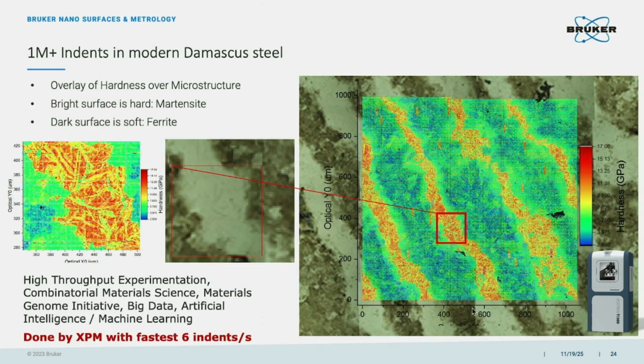So this is the example. We are using our indenter to do the high-speed mapping. We call it 1 million indents. Of course, this is extremely too much, 1 million, right? But just to give you the idea, because we are going very fast, right? Maybe 100 indents take just 30 seconds. So for 1 million indents, probably we need several hours, right? But even several hours is still very fast for 1 million data points.